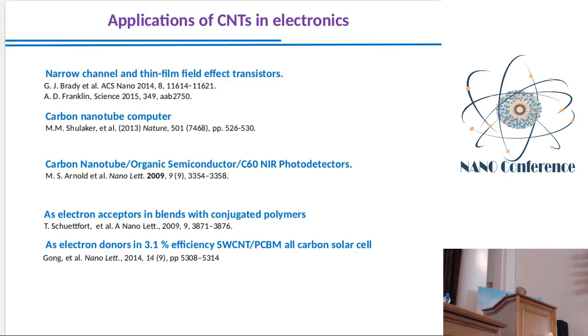They were used also as electron donors with PCBM blends in all-carbon solar cells, and quite substantial efficiency, 3.1% efficiency of solar energy conversion, was achieved in these materials. Okay, so for further applications, we of course should understand very well what's going on under excitation of such composite materials. And as I will show later, these processes are not simple, and quite many processes take place when we excite carbon nanotube and PCBM blends.